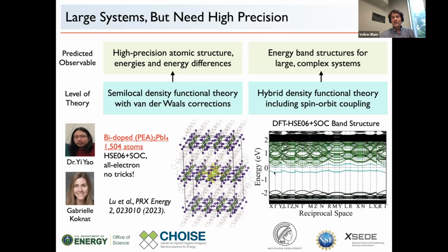Unfortunately, this defect level is about 0.5 electron volts below the conduction band. So this is actually a relatively deep dopant, not a shallow dopant, and you have to put a lot of bismuth into the material to make a small difference. But nevertheless, we can do this type of calculation directly, and so the energy levels come out where they should be, in what the experiment agreed with in this case.